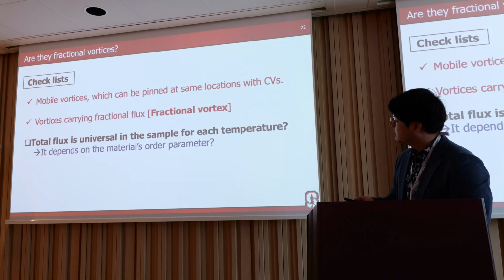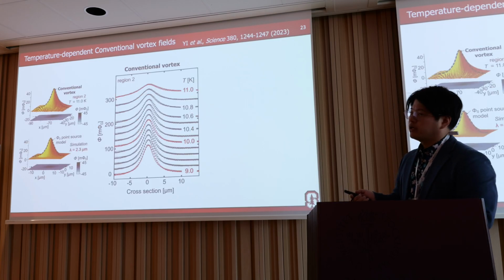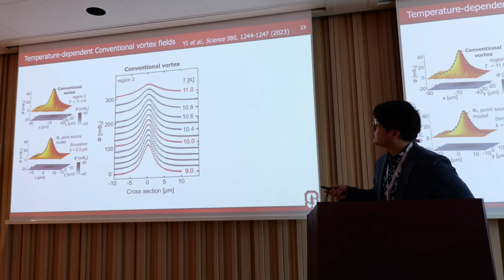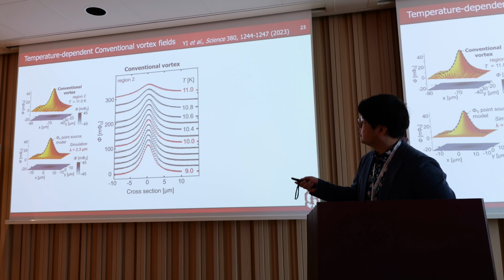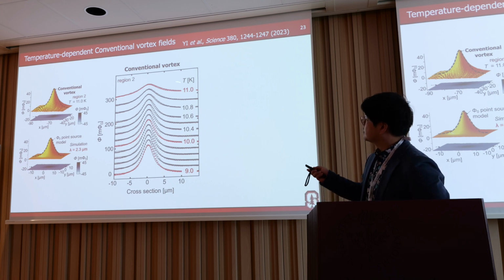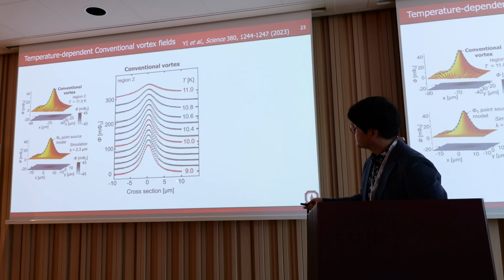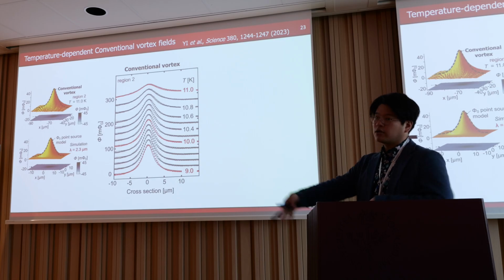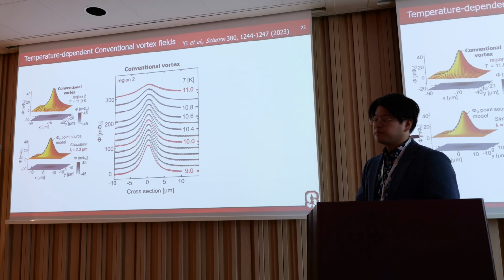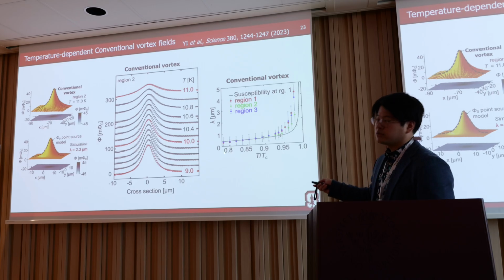But the temperature dependence is more dramatic. This is a cross section of the integer vortex. As expected, at lower temperature the magnetic field is more localized, because the penetration depth is shorter at lower temperature.